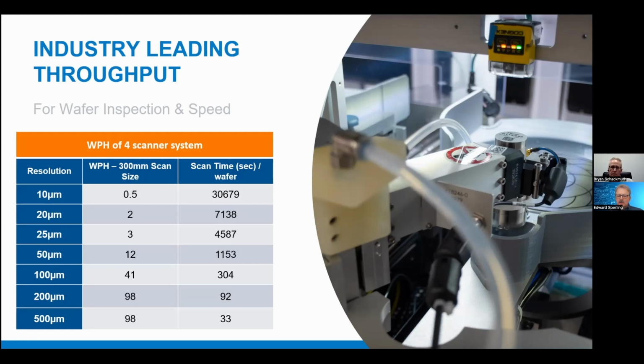Is that all because you need higher resolution for smaller features, or is it also because now you're looking inside a package, saying, hey, we have heterogeneous integration going on here with lots of different chiplets? Yeah. So as they stack for HBM, they'll have an 8 stack, even up to 16 stack, through silicon via, depending on the type of bonding. There's a thermal compression type bond, or an underfilled, molded underfilled type bond. The feature sizes in those various methods for HBM vary, but essentially, as time progresses, they're going to be getting smaller. Right now, we're going down to 10 microns as our finest scan pitch.